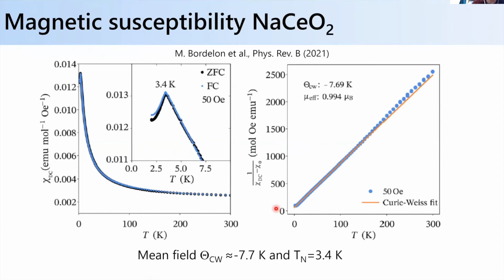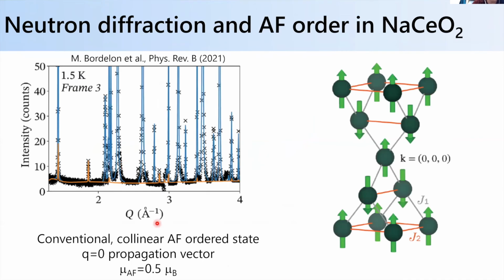And then if we look at susceptibility, in this case, we see this rather sharp cusp at 3.4 Kelvin, indicative of ordering. And it's slightly frustrated. If we look at the Curie-Weiss analysis, it's -8 Kelvin. So it's a little bit frustrated, but there seems to be a clear onset of magnetic order. And indeed, when we solve the magnetic structure, it acquires a conventional sort of collinear antiferromagnetic order ground state. So this Q = 0 propagation vector with the moments oriented along the long c-axis, okay?